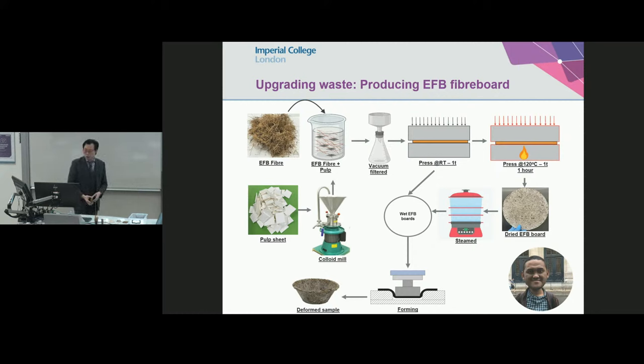So what we did essentially was we take these empty fruit bunch, we combine them with your pulp fibers, blend everything together, squeeze out the water, and what you get is a rather stiff fiber board. And this one has 30% pulp fibers and the rest are just your waste empty fruit bunch. Rather stiff, rather strong. Without it, it's basically quite bendy, right? So without that pulp fibers to bind everything together, it's quite bendy. So you do need to have that cellulosic structures in there to bind everything together.